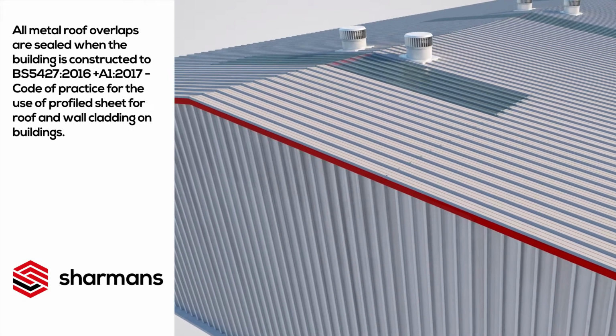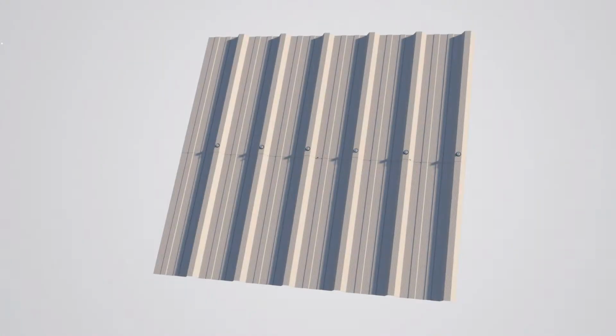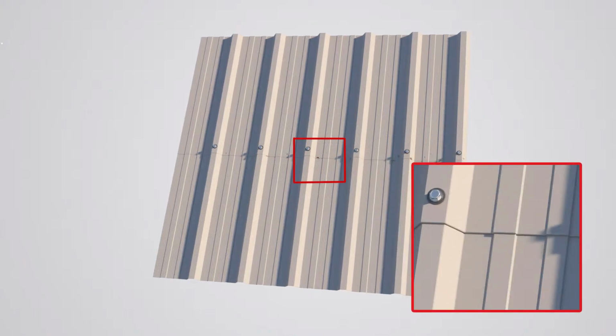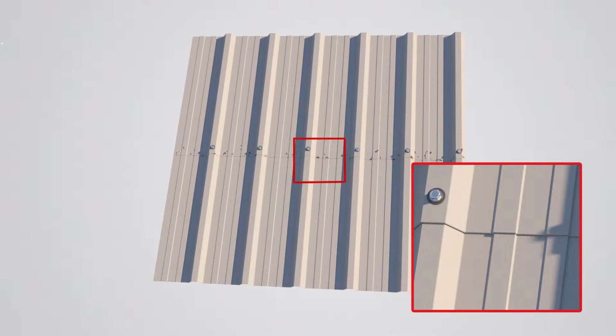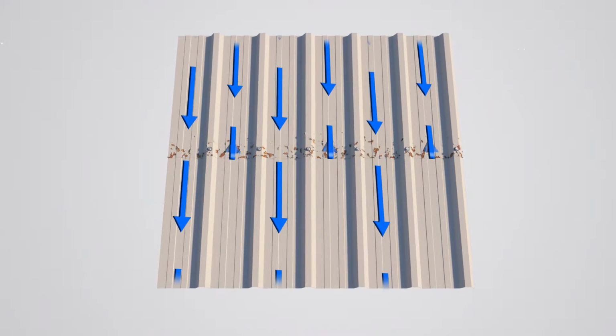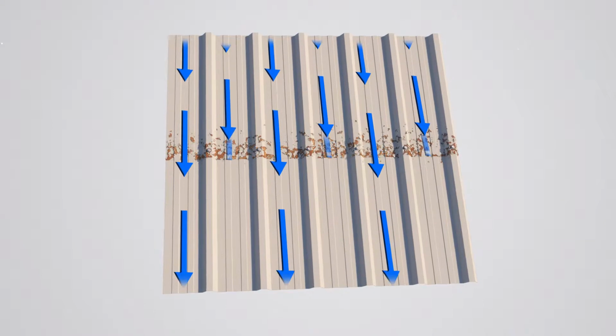the correct time, and in line with the original British standards to which it was built. Special attention should be paid to roof sheets, as they typically show the first signs of needing attention. The cut edge and overlap joint is especially vulnerable during phase 1 of the aging process due to the effects of capillary action. This draws sulfur-contaminated rainwater into the joint, which causes the double hazard of topside and reverse side